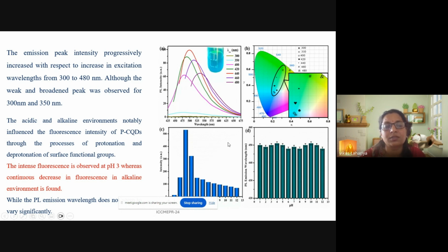Further, the fluorescence behavior is utilized for the pH sensor, where the fluorescence intensity changes with changing pH value, while the emission wavelength remains the same, and the highest PL intensity is found at pH 3.